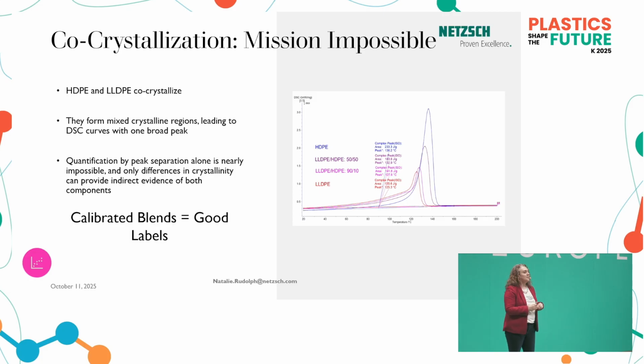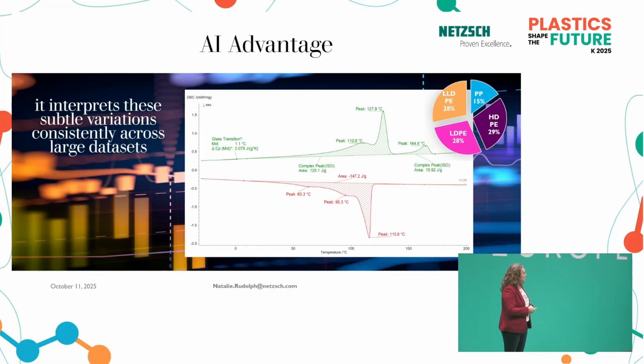Maybe I should say that we trained the model, and then we added more data, and the model got worse. So, that was not what we expected. It was a lot of data. And then we realized that during the data processing, some mislabeling had happened, and PP was classified as HDPE and vice versa. And then the model really didn't know what HDPE and PP looked like, because in one data set, it said HDPE, in the other it said PP. And once we found that mistake, it even improved. That was the intention we had.